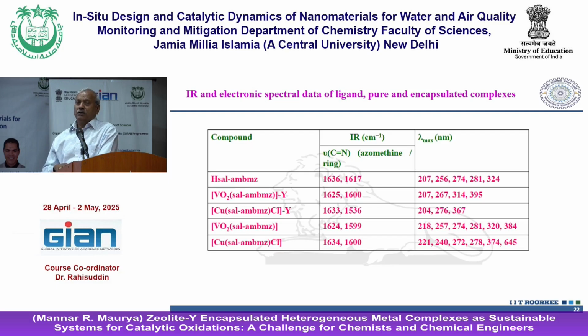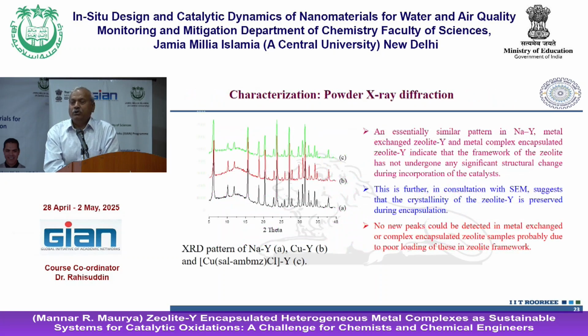And then characterization by powder XRD. People have used powder XRD very frequently to characterize it, but frankly speaking, this does not give any information related to the metal encapsulated complex. What information does XRD give about the crystallinity of the zeolite? Whether you have NaY is perfectly crystalline, all peaks are coming due to it, because you know that crystallinity means peaks are sharper, right? So from first to second to third, what you get is that even after exchange of the metal ion, crystallinity is maintained.